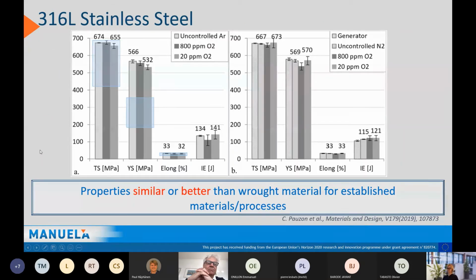However, does that matter? Well, the interesting thing, if you look at the 316 stainless steel here, you see an example where we have used standard argon atmosphere, 800 ppm oxygen and 20 ppm oxygen. That is where you have this type of specific oxygen control during the build. Now, stainless steel is usually what we say is an easy-to-build material. If you look at the properties, this is built well in all these conditions, and we see that the tensile strength and yield strength are actually similar, even better than wrought material, for established materials and process.